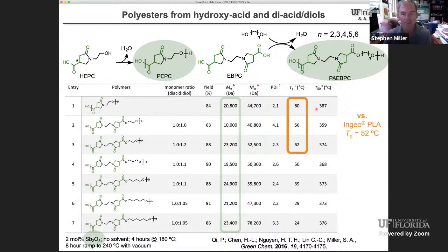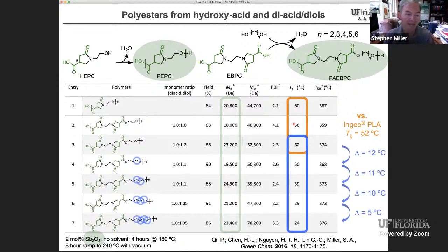The glass transition temperatures, when the ethylene spacer, the alkylene spacer, is short, tend to look like that of PLA. So PLA is in the 50s. We get maybe 60, 62 degrees for the Tg of some of these. So in terms of glass transition temperature, it looks quite comparable. If you add more methylene spacers in your comonomer, you only serve to ruin your glass transition temperature. That lowers it by about 5 or 10 degrees per additional methylene group. So in general, you want to use ethylene glycol with this in order to keep the glass transition temperature high.